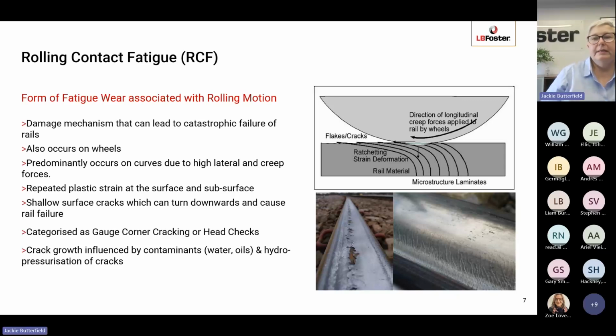So this damage mechanism really came to prominence after the Hatfield train crash in 2000, in which a high-speed train derailed and 4 people died and over 70 people were injured. And the following investigation identified that the rail had fractured in several places due to rolling contact fatigue damage. So it can be a catastrophic failure of rails. It also occurs on wheels as well as the rail.